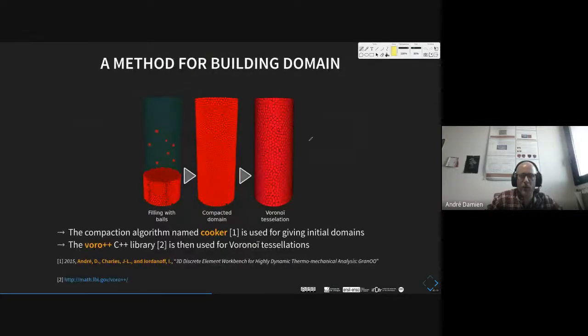So just a few words about how to build a discrete domain that is compatible with such an approach. What we do in GranOO, but there is, I think, a lot of ways to manage this. We use what we call the compaction algorithm, which is named Cooker. It is a simple way to get a compact domain with spherical discrete elements. From this compacted domain, we simply apply a Voronoi tessellation thanks to the very simple and accurate Voro++ library. So now we are able to have Voronoi domains which are compatible with the DLSM method.